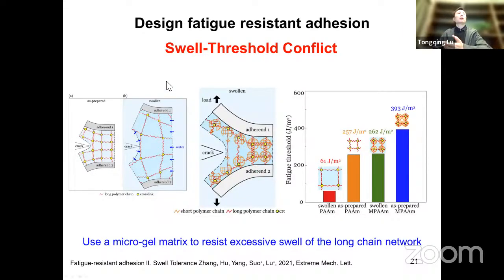Another problem we need to solve, and we found in our experiment, is that when we define this fatigue resistant adhesion, because we use hydrogel here, when we use very long chains, there is the first conflict, we call it a stiffness threshold conflict. Actually, there's another conflict, called the swell threshold conflict, because usually this adhesion structure will be used in some liquid environment, for example, in the human body or in some animal body tissue environment. So there's water around. The water molecules will move in and swell this interface and cause fracture, or at least reduce the fatigue property of this interface.